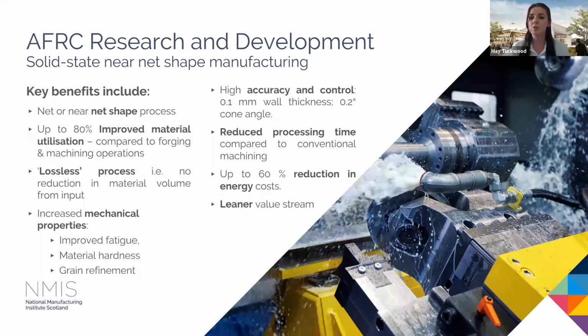We've got a huge amount of material utilisation as compared to conventional forging and machining, up to 80% improvement. It's also a volume constant process. So the volume of that preform going in is equivalent to the part that's coming out. And our processing times, I should mention, are very quick. So in terms of your conventional machining routes, we mentioned that earlier on in terms of the flow forming of shafts, and the amount of machining time to do the hollow bore on shaft components is significant compared to an up to 40-minute cycle on the flow former. Some of our smaller components or some of the conical parts, you're talking a 3-minute cycle time. So compared to your conventional processes, significantly improved.